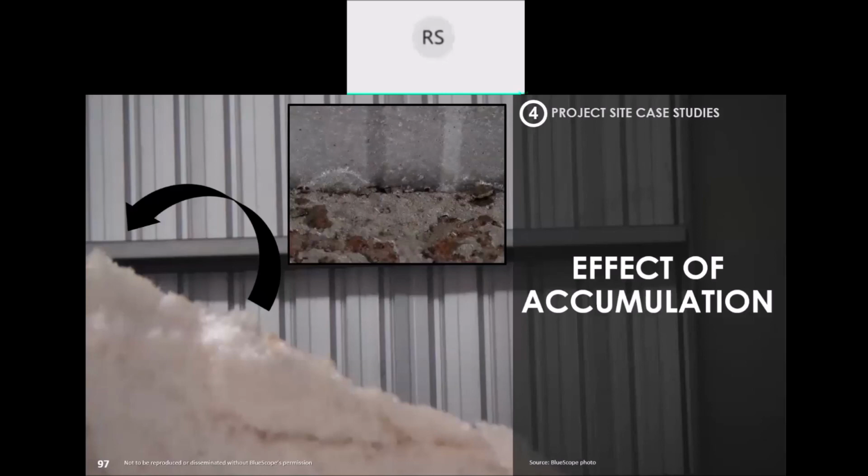One of the buildings that we studied in this example is a salt manufacturing plant, basically a salt producing plant. What happened was that some of the fine salt got airborne and accumulated onto the structure near the cladding. What you can see from this small photo is that the cladding itself and also the structure have started reacting with salt particles, because it's not being diluted away, right?